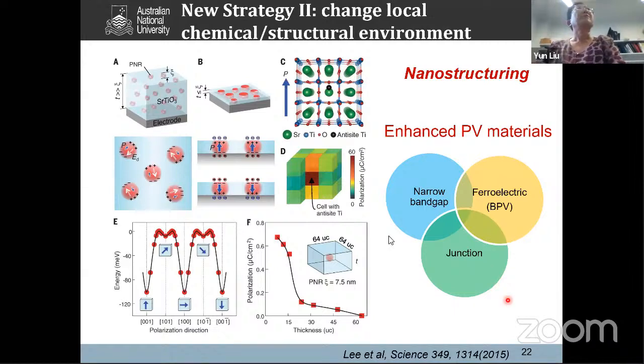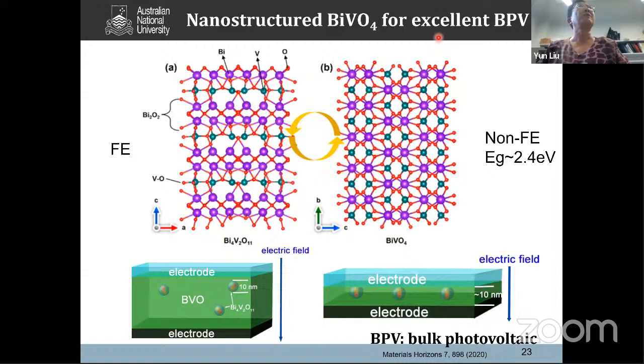So for that, for example, we choose bismuth vanadium oxide, which is generally a non-ferroelectric material with a band gap of 2.4 eV, and you can chemically introduce local chemical nanoregions, which is Bi4V2O11. So in that case, it is ferroelectric. So these two materials you can switch by controlling the synthesis condition. So as a result, you can reduce the thickness to a height similar to the polar nanoregion.